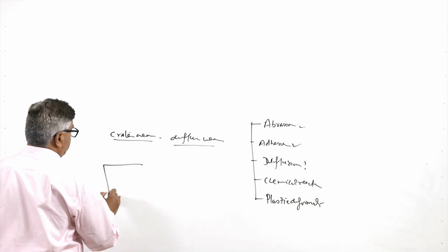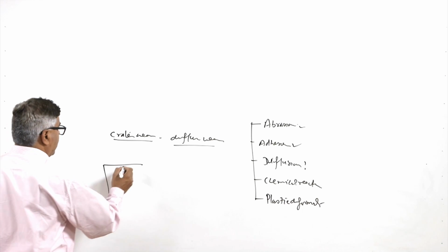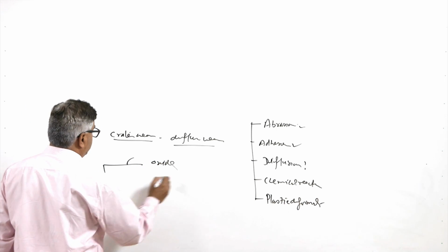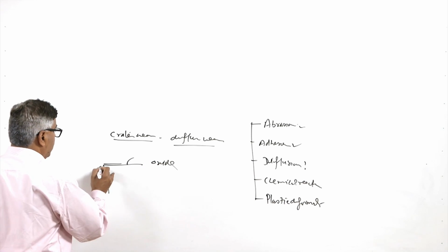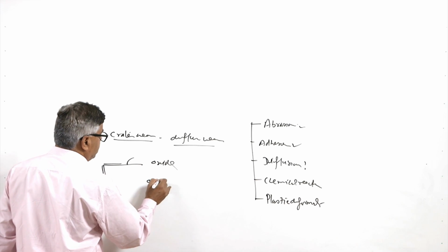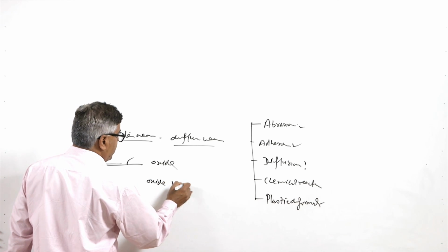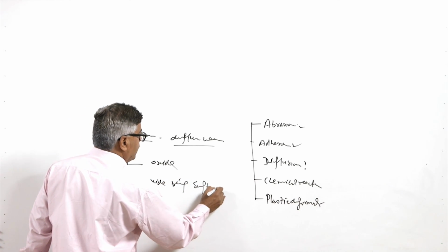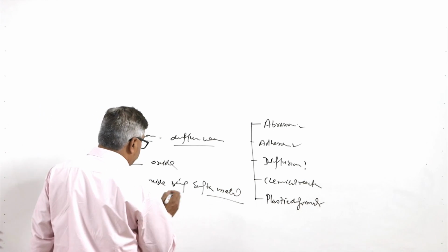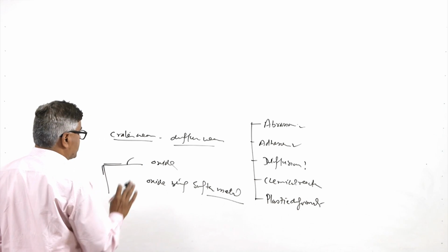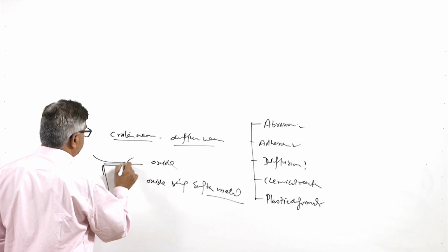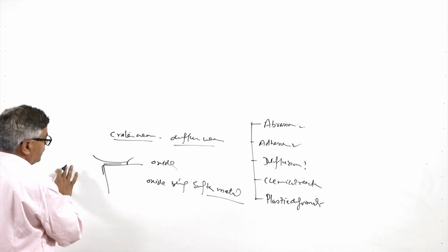Chemical attack is the simple form, where the rise in temperature of the rake face of the tool causes oxidation. An oxide layer is formed at the face and the flank of the tool, and since some of the oxides are softer than the base metal of the tool, they are easily removed during machining, due to the movement of the chips over the face of the tool or the rubbing of the flank with the workpiece.